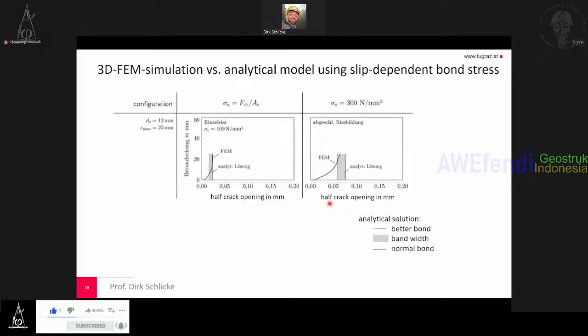If we go further, we can now check the crack opening over the concrete cover, and we see here for a concrete cover of like 25 millimeter, the analytical solution with a bandwidth of good and normal bond compared to the FEM simulation, which is this curve, compare quite well to each other at the surface. The same happens if you have an increase of the steel stress, which is then 300 Newton per square millimeter, comparable to surface life conditions usually. This at crack formation, this is for surface life condition. We also have a good agreement.